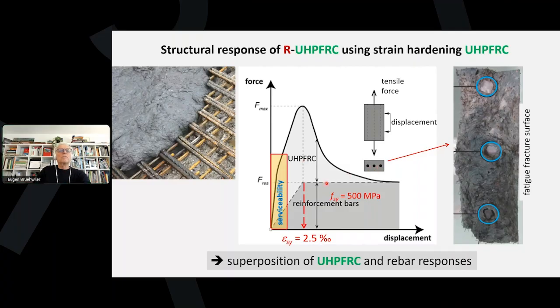Now, the material R-UHPFRC relates to the presence of rebars. And mechanically, we add the response of the reinforcement bars, which is schematically this line, to the response of UHPFRC. And UHPFRC has a deformation at maximum tensile stress which is around the same deformation at which the reinforcement bar enters into yielding, which is at around 2.5 per mil of strain.